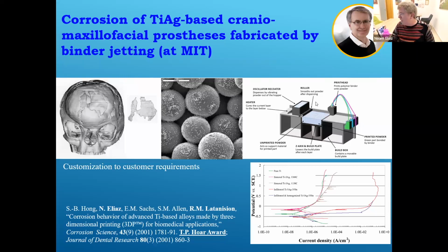On the right-hand side, at the top, you can see the principle of binder jetting. You spread the powder, and then you come with the print head, and you can use either organic or inorganic binders. According to your file, you just drop the liquid or the binder in the areas that you want, and then you lower the build plate, and this way you build the whole part layer by layer. Later, in this case, you do either sintering or liquid metal infiltration in order to densify the material.